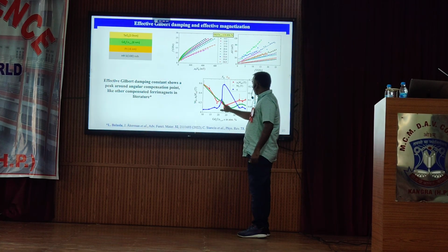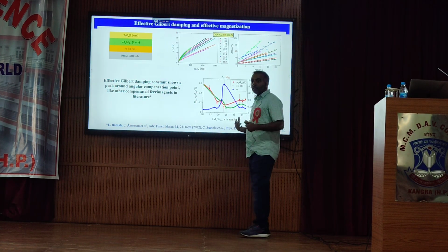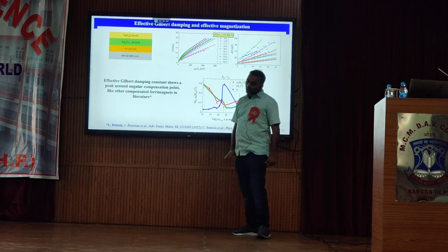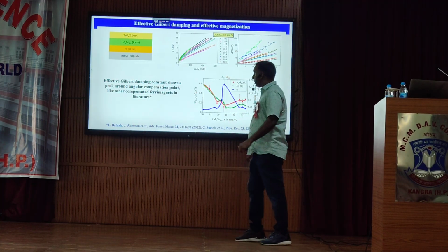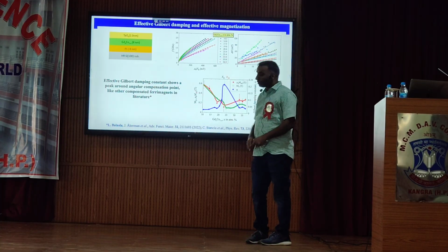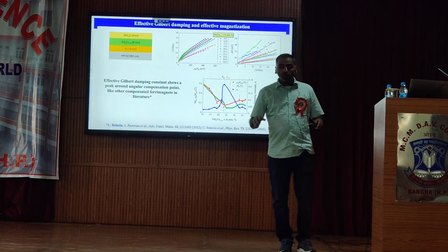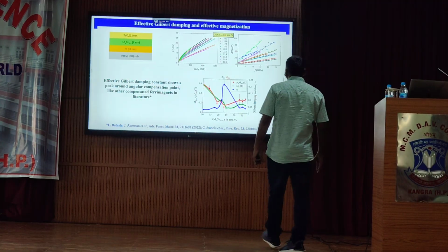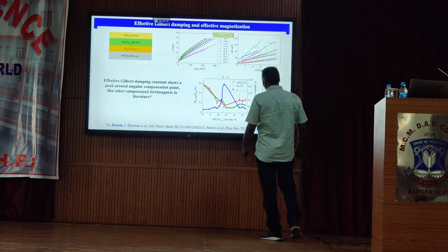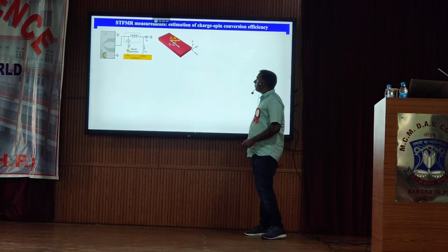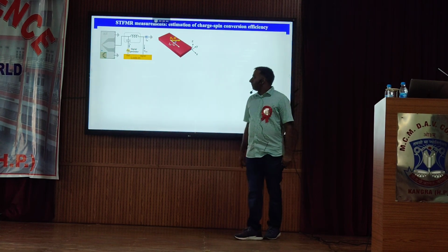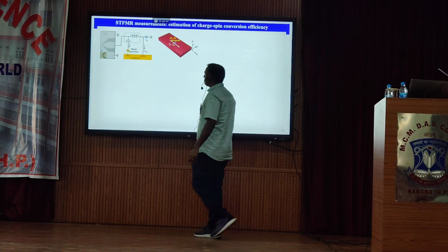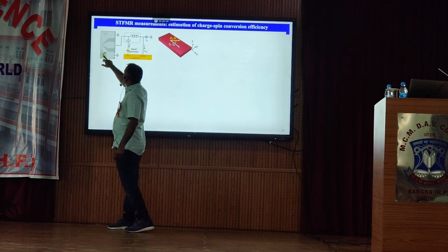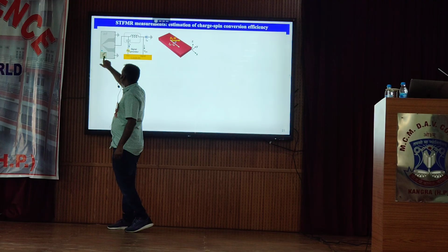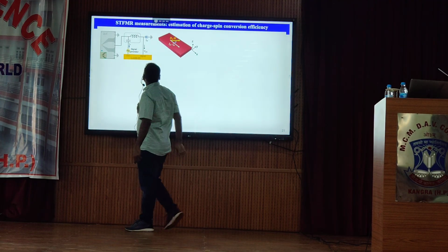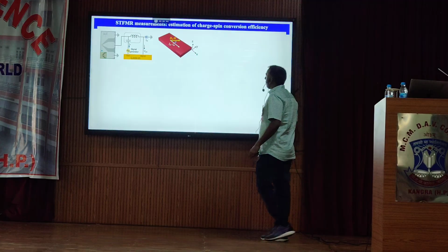Once we confirm that this composition around 25% is nearly vanishing, we choose around 3-4 different compositions near this point to make the devices. So far we have not made any devices. Those measurements were performed on thin films grown on a large area, like 10 by 10 mm squares. Then, once we confirmed that our thin films are of high quality and show the angular compensation point, we made the devices, like microchips or rectangular chips of the samples shown in this schematic, and we use this kind of setup to measure again the spin orbit torque of our devices.